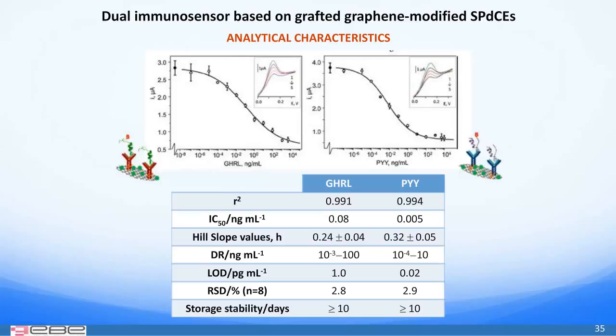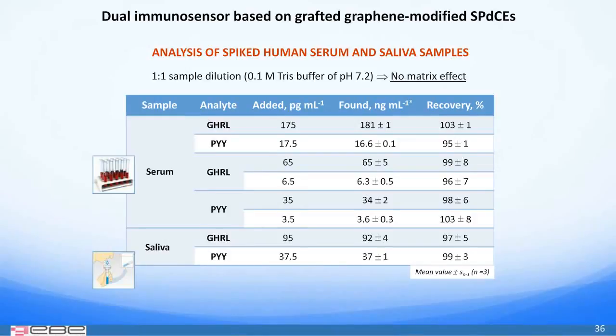Results obtained demonstrate also the reproducibility of the fabrication and functioning of the proposed immunosensing platform and their storage stability during at least 10 days. After demonstrating an excellent selectivity for both hormones against other proteins and the absence of cross-talking between the two target hormones and the two adjacent working electrodes, the applicability of this immunosensing platform to the analysis in spiked human serum and saliva samples was evaluated.